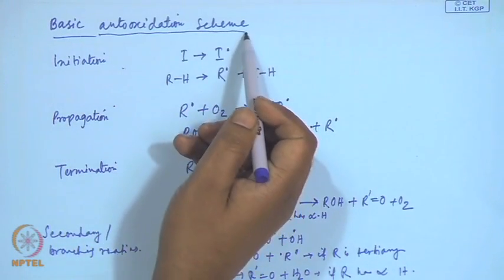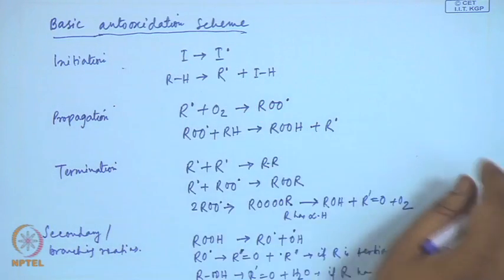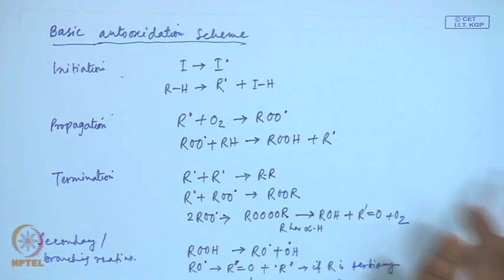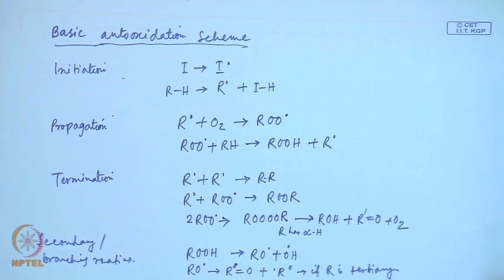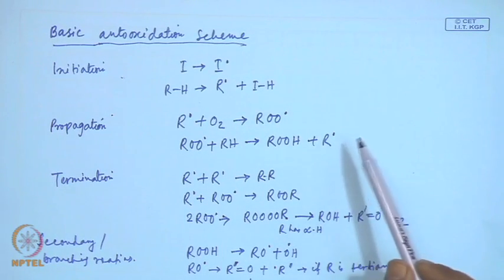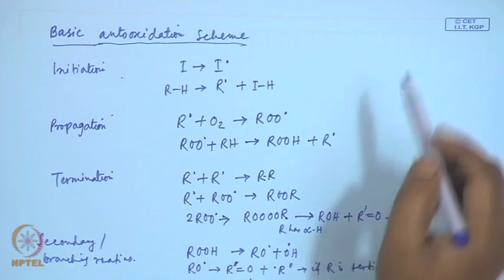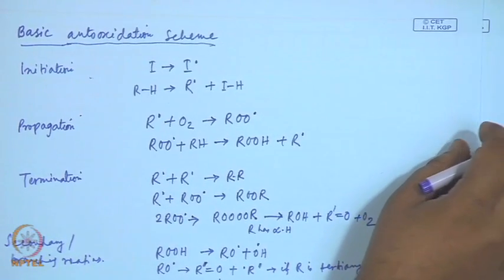So, these are the basic auto oxidation mechanisms by which oxidative degradation might happen. As you can see, it's a radical process. Now, to prevent this, if you want to design an antioxidant, you basically have to attack or stop all these processes. Antioxidants are added or designed which cannot prevent all these steps, but might prevent some step in between.